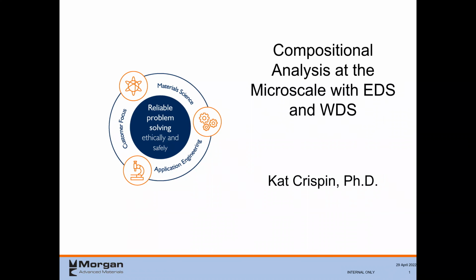Nice, cool. I saw another question that came in as well. They're asking, since the signal data is produced both by electrons, does interaction volume differ greatly from EDS? Are there probe energy pitfalls? Not sure. So the interaction volume is the same between EDS and WDS because the X-rays are coming from the same volume. If you're doing a one-to-one comparison using the same accelerating voltage, so like let's say you use 15 kV, which is a typical accelerating voltage, the interaction volume is going to be exactly the same whether you're using EDS or WDS. So there's no difference there.